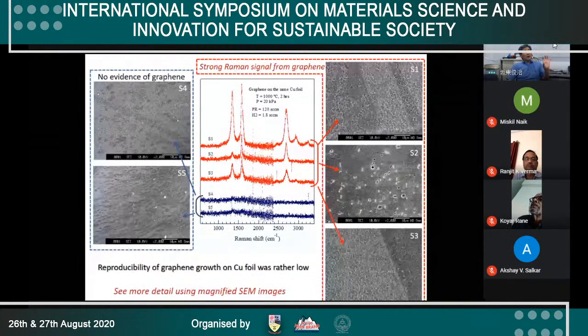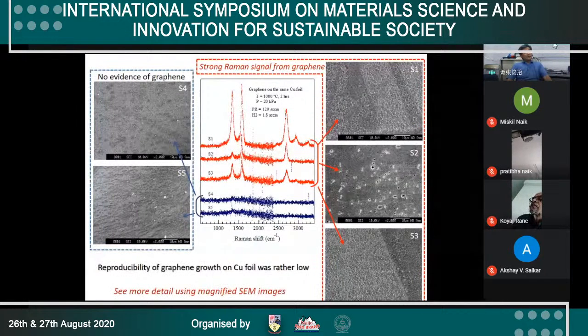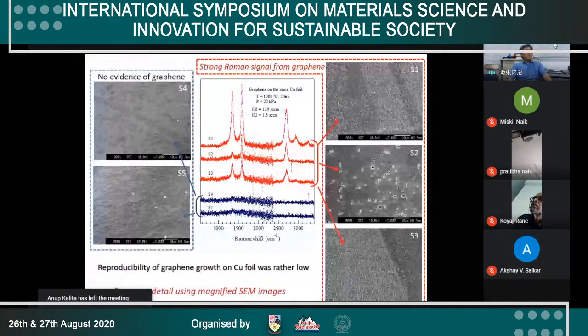If we anneal the copper foil, in such a case, sometimes the graphene grows well, but sometimes not. The center part is the Raman result, and both sides are scanning electron micrographs of the same sample. To see more detail, we use the magnified SEM.